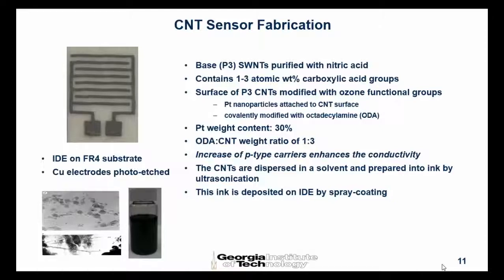So some details on the fabrication. I don't have much time to go through this. I don't really like to put a lot of things on the slides, but because it's 15 minutes, I have to put this so at least you can read it. But basically, we are doing two functionalizations: platinum decorated nanoparticles, and then covalently modified ODA molecules. So this is an organic molecule, and these are platinum nanoparticles on the surface of the nanotubes. And we basically synthesize it in the form of an ink. So we make an ink from these nanoparticles. We put it in a solvent and make an ink, and then spray coat the electrodes.